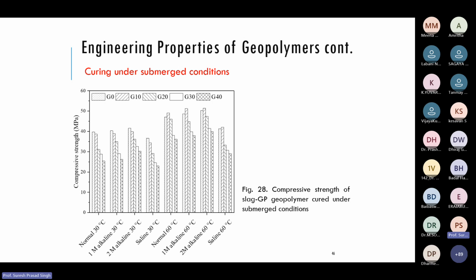So if curing is to be done by putting the specimens in water, like other conventional methods, it should be alkaline water, so that leaching will not occur and balancing will be there, with the concentration of the alkaline material outside and inside being balanced. So the loss of sodium hydroxide will not be there.